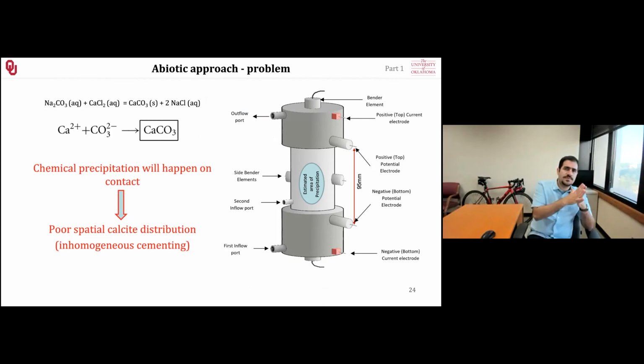So to those people, I would say, all right, remember, if we don't have any agent in the subsurface to take this cementation agent with it and precipitate it in the smallest pores, then we're going to get a poor distribution of cementation. Basically, whatever is happening is at the zone where we are mixing these two chemicals, at the zone we inject, not everywhere else. So how do we overcome that? To overcome this problem, we're going to use microbes.